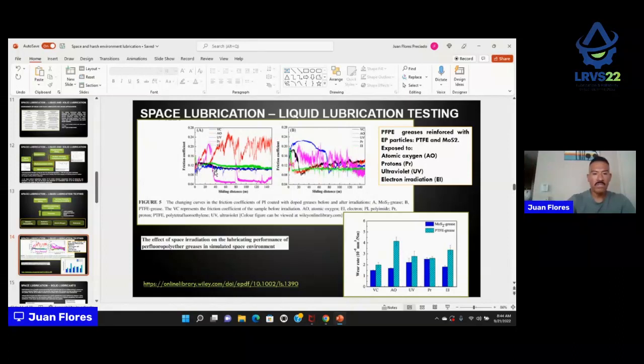So when they did that, they observed significant changes in the coefficient of friction due to the interaction of the grease's components and the different radiation systems. In this case, they tested PFPE with molybdenum sulfide and then PFPE with PTFE particles. So once again, your grease is extremely fancy, it has a lot of chemicals, but guess what? The PTFE is not very resistant to atomic oxygen. So I'm reducing the quality of an expensive grease because I'm adding PTFE particles. It may be good under some applications, but it's not good if it's exposed to radiation. So again, that's something that we have to take into consideration that we normally don't care about in a terrestrial environment.